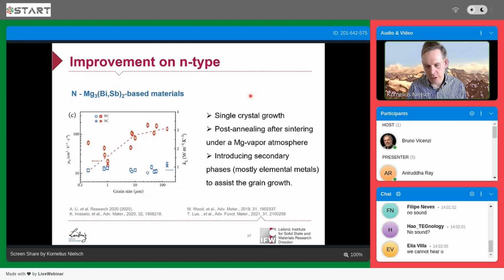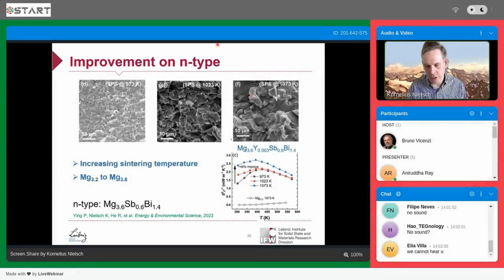But nevertheless, if we optimize the synthesis approach and obtain large crystals, the mobility of the electrons increases. And by this, the overall electronic properties are superior. One of the strategies to improve the crystalline phase was optimizing the compaction by spark plasma sintering. You can see here a series where we applied different temperatures, starting from 973 Kelvin, going up to 1073 Kelvin. You can see the crystal size was significantly improving. And if you look, for example, at the thermoelectric power factor, the Seebeck squared times the electrical conductivity, you can see a significant improvement of up to 46%, for example, in the results at room temperature.